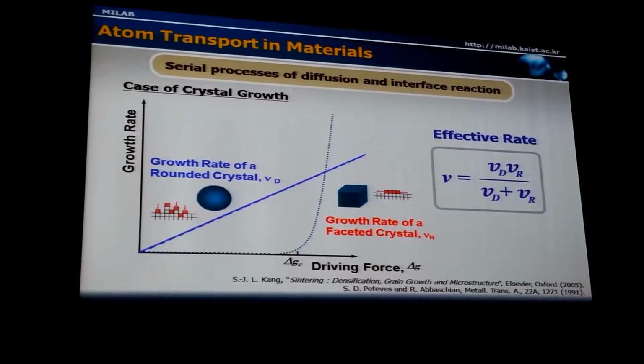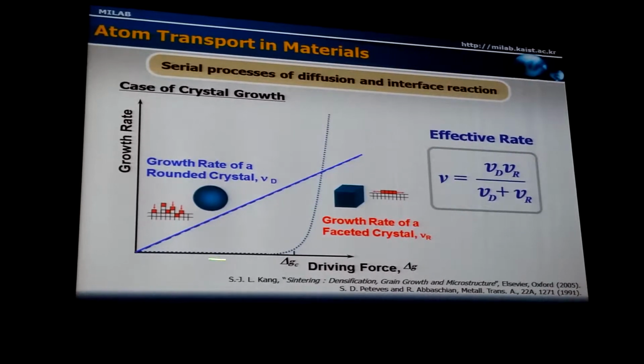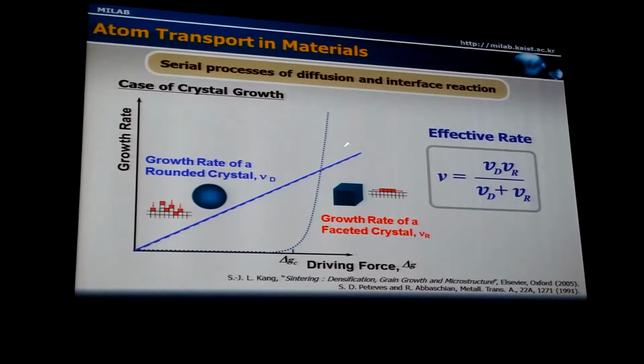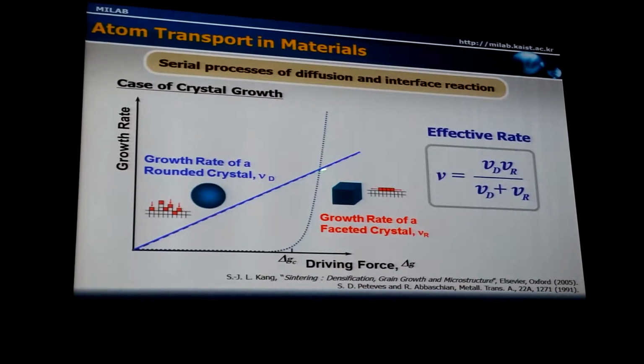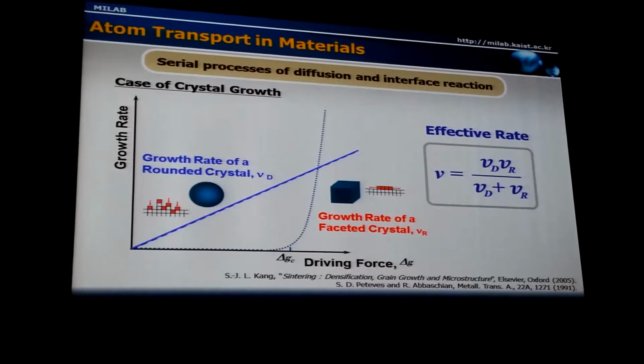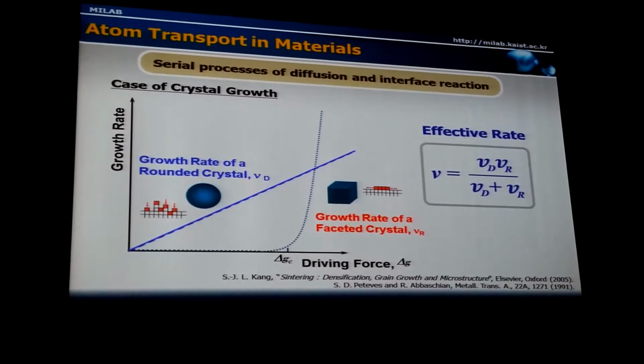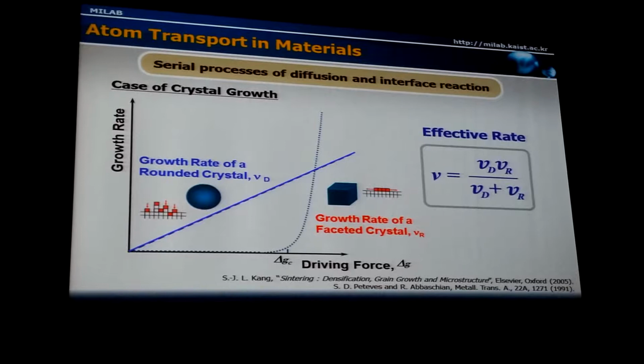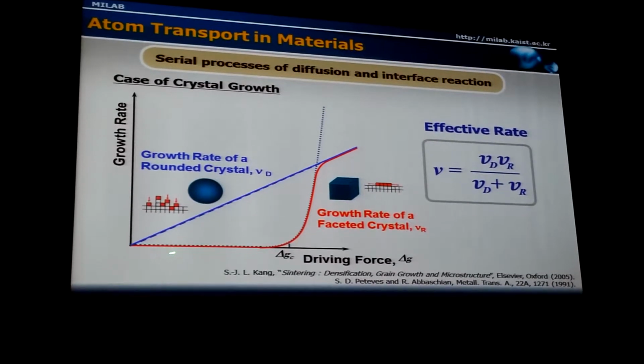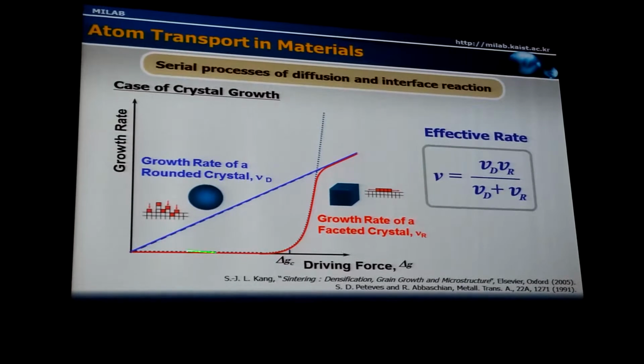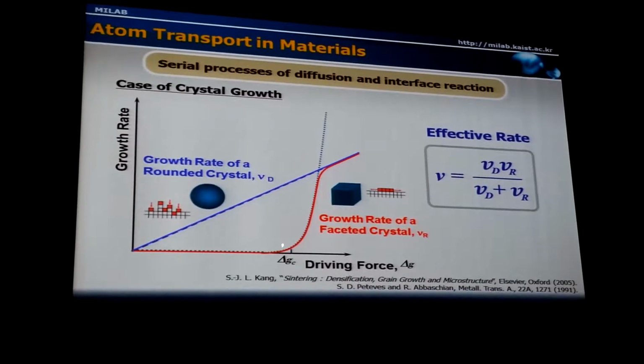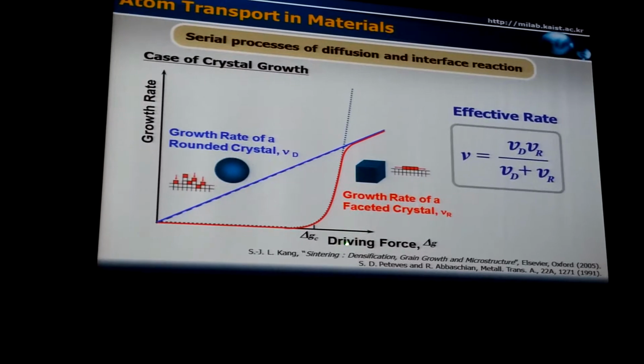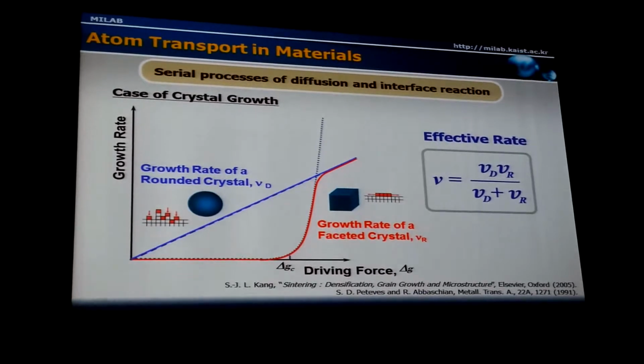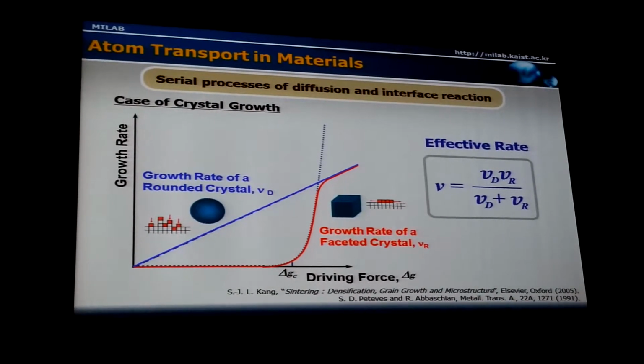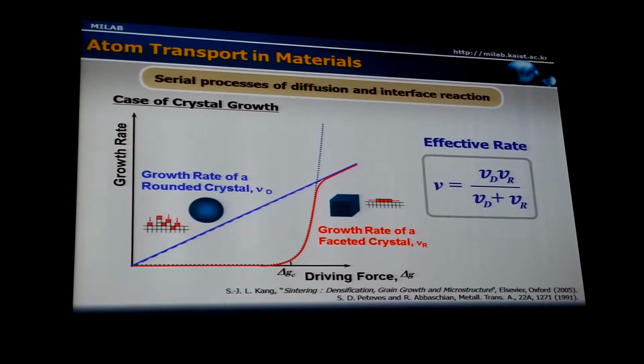That means there is a region where the interface reaction rate is slower than the diffusion rate, and another region where the diffusion rate is smaller than the interface reaction. Therefore, as the characteristic of serial processes, the slow process governs. When the driving force is smaller than the critical value, the growth rate must be governed by the interface reaction. And if the driving force is larger than the critical value, the growth rate must be governed by the diffusion, showing a nonlinear growth behavior of the crystal.